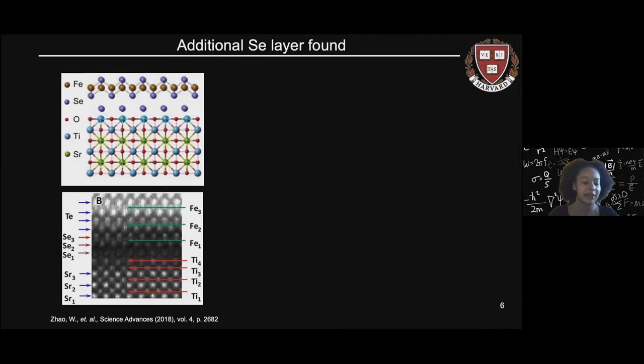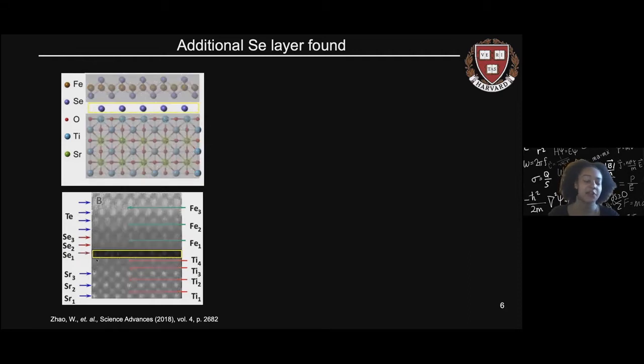So one study here conducted in 2018 employed scanning transmission electron microscopy, or STEM for short, to produce an atomic resolution image of the interface. You can see here they've located all of the different atoms and labeled them. And the main interesting conclusion of this study was they located an extra ordered layer of selenium at the interface, shown here in their STEM image, as well as in their crystal structure.